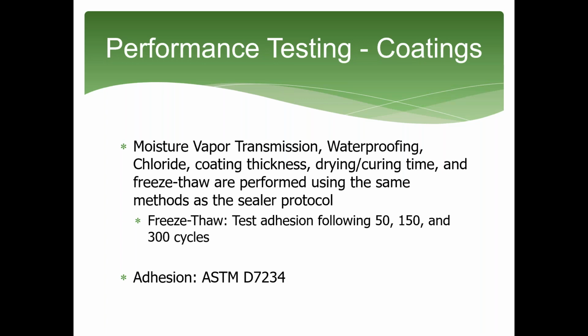Moving on to coatings. For the coating type sealers, the moisture vapor transmission, waterproofing, chloride, coating thickness, dry time, and freeze-thaw are all tested by the same methods as the sealers. However, the only difference being that the tensile adhesion is tested following 50, 150, and 300 cycles. Adhesion is tested by the pull-off test. ASTM D7234 specifies the use of 2-inch pull stubs.